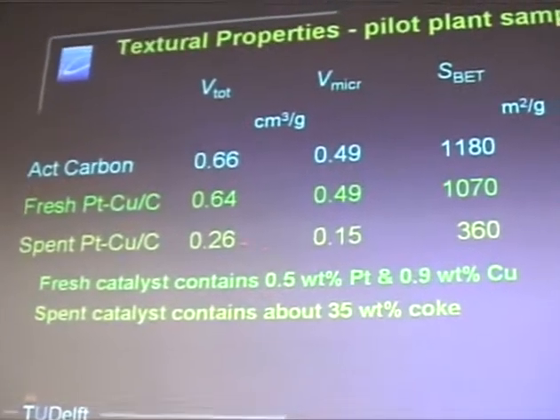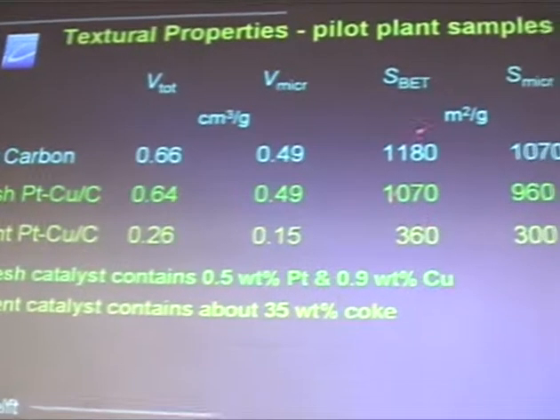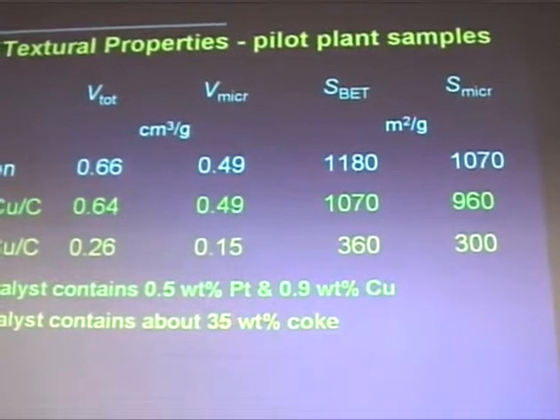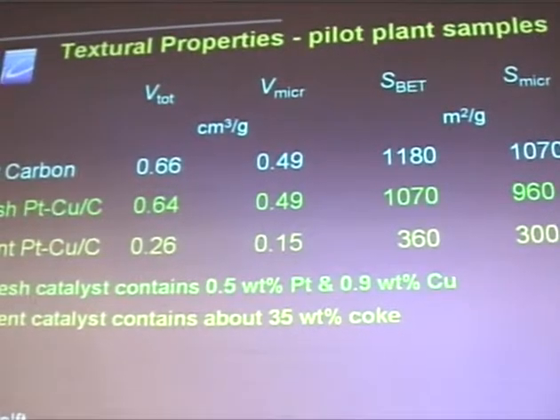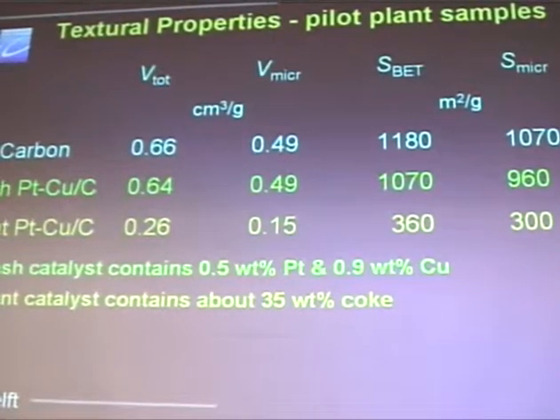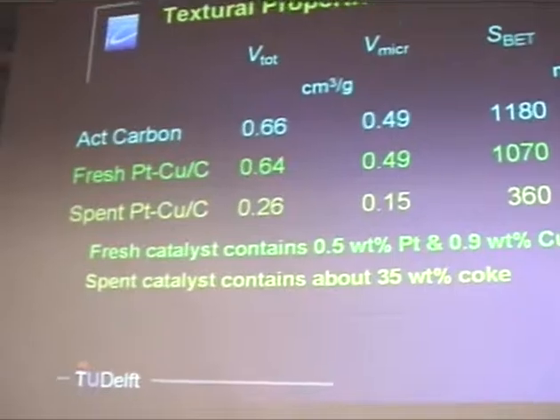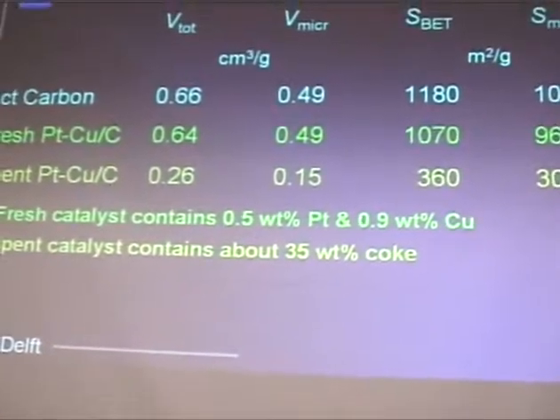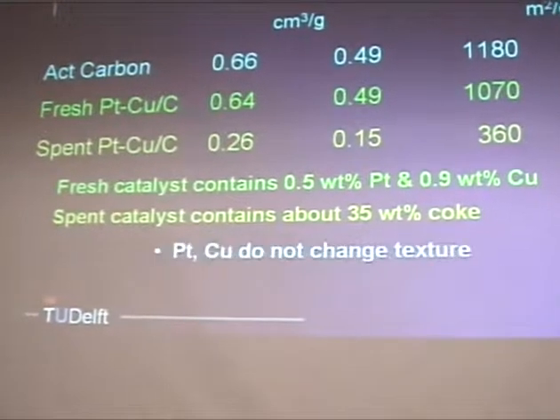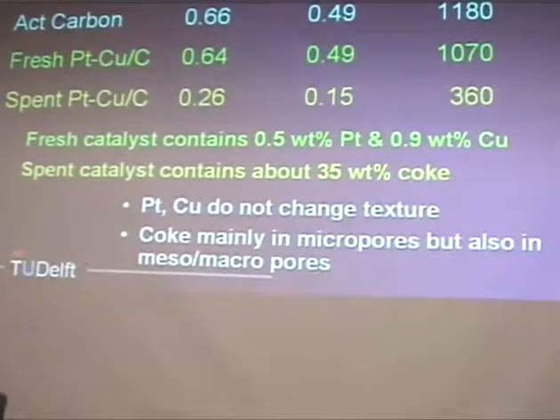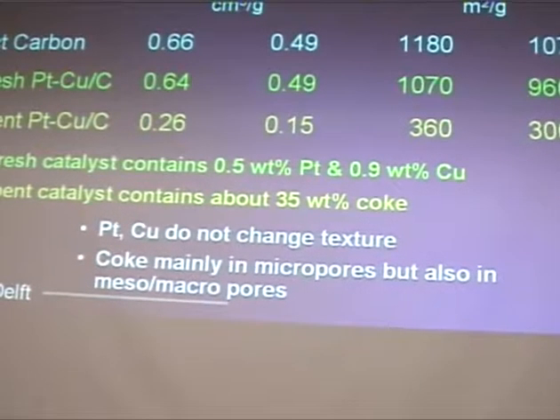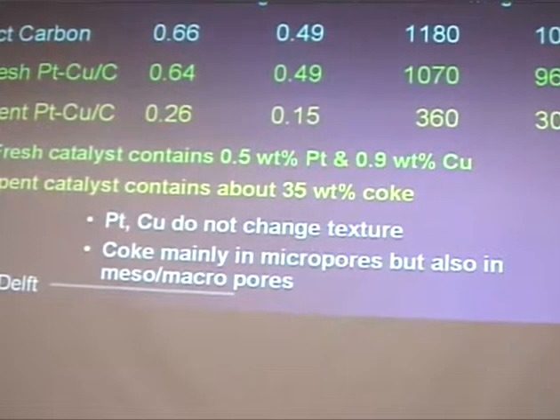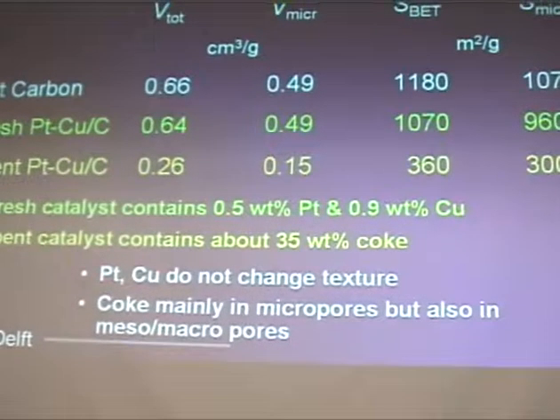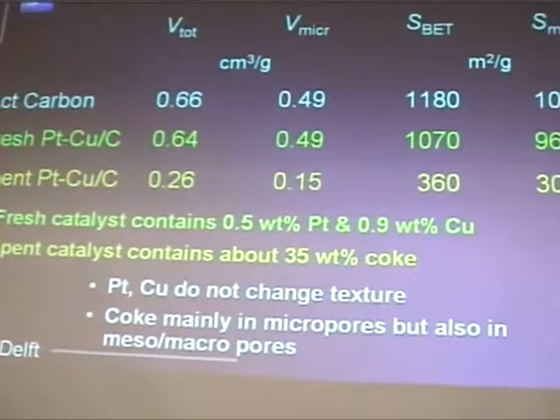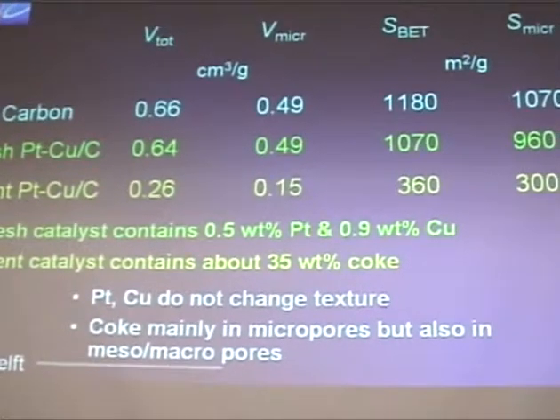The spent catalyst has much lower porosity and surface area. It contains about 35% coke, quite a lot. The porosity goes down by more than 35%, so you block a lot of pores, especially micropores. So the platinum-copper system does not change the texture, as you would expect, with coke mainly in the micropores, but also in the mesopore system. That gives you a picture of the system.